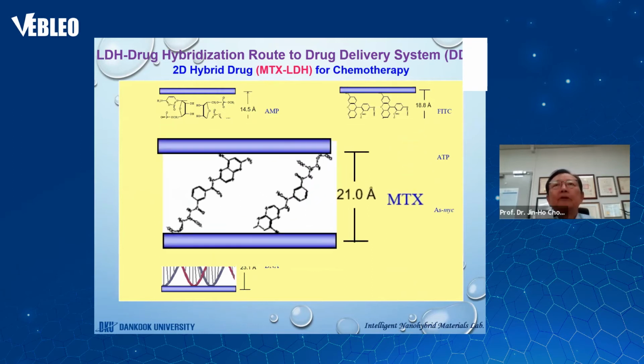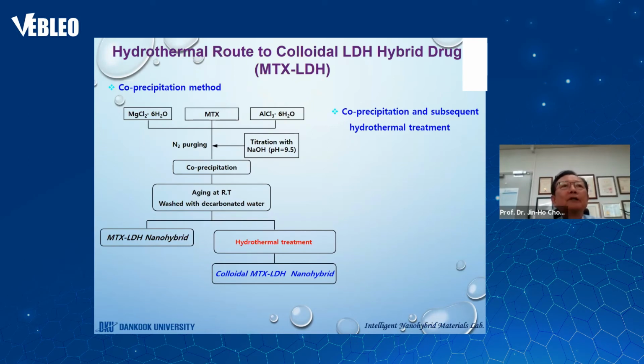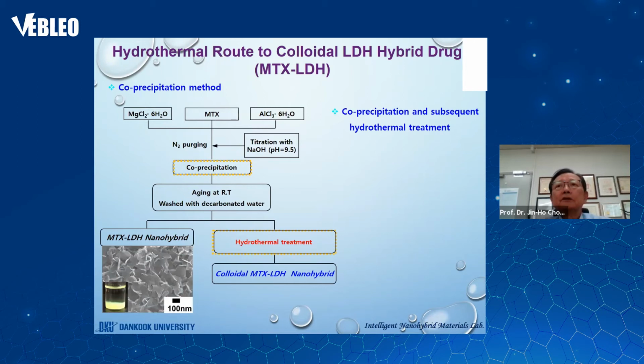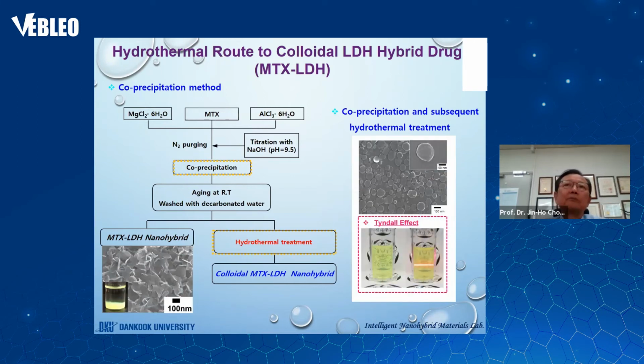Based on these in vitro experimental results, we decided to prepare a chemically well-defined MTX-LDH nanohybrid. It's a nanohybrid drug with an excellent colloidal property to eventually be injectable for in vivo experiments. MTX-LDH nanohybrid was prepared by the co-precipitation method, as I mentioned in the beginning of my talk, and the precipitate was further hydrothermally treated to obtain a colloidal drug by controlling the hydrothermal conditions, such as reaction temperature and time. The reaction temperature was around 100 degrees C, and it was treated under hydrothermal condition for 6 hours.